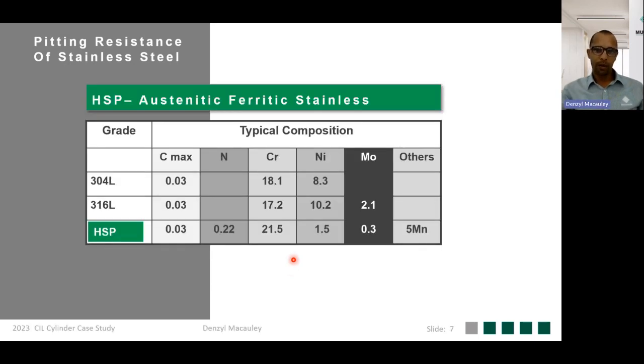Again, HSP, molybdenum content 0.3, 316, molybdenum content 2.1. But the manganese content was very interesting for us. We thought that because in mining applications manganese work hardens, the material would become hard after working for a while. But be that the case, we tried to reduce corrosion in this instance, and not so much wear. What was really interesting was we received some feedback a few weeks ago that 316 was actually the go-to material in this application.